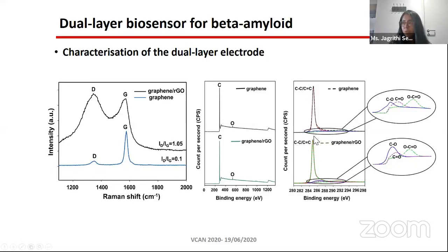And next is the XPS spectra, this is the overall scan. Here we can see that the intensity of oxygen in graphene is lower compared to the graphene RGO structure. The percentage of oxygen increased from 1.4 to 2.4 for graphene RGO. It's not as high as in graphene oxide structure, but that's because of the reduced number of oxygen functionalities in reduced graphene oxide. Then this is a C1s scan for graphene and graphene RGO. Here also we see an increase in the intensity of C-O bonding, but not anything else like C=O or O-C=O. That is also because of the reduced number of functionalities in reduced graphene oxide.